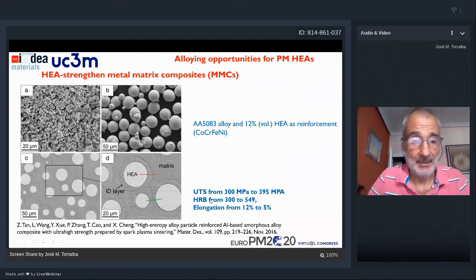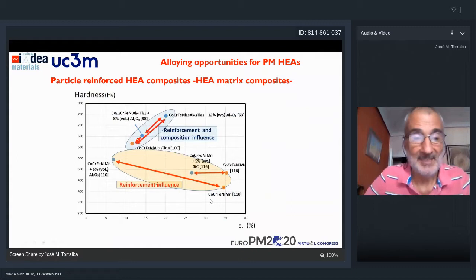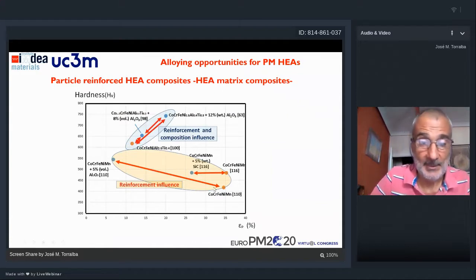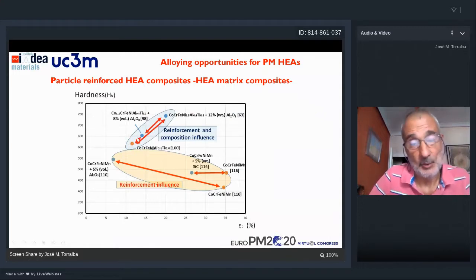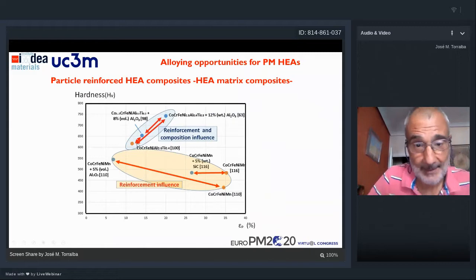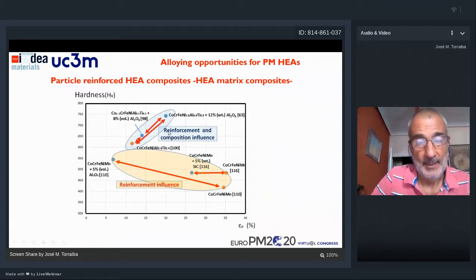Another possibility is the opposite. The high entropy alloy could be used as matrix, and we can use as reinforcement ceramic materials or intermetallics or any others. And this way of alloying, which is typical for powder metallurgy, is not possible to do in another alternative processing method. We can increase the tensile strength or the hardness, and sometimes we can increase hardness and at the same time elongation. In that case, we have reduced the elongation, but in this other case, in this area, we can see how we can increase hardness and elongation.